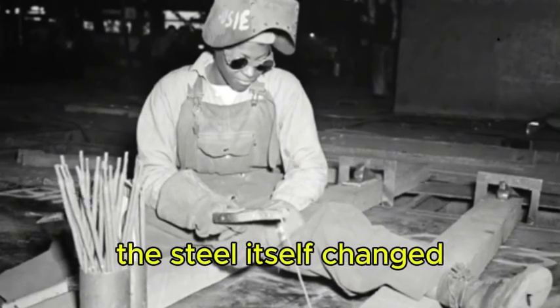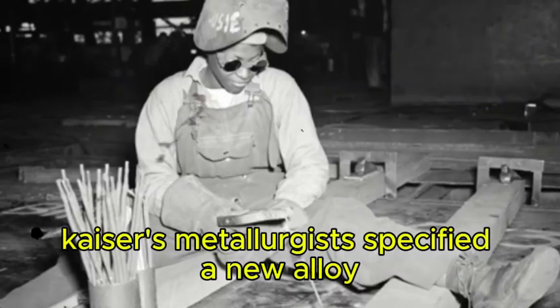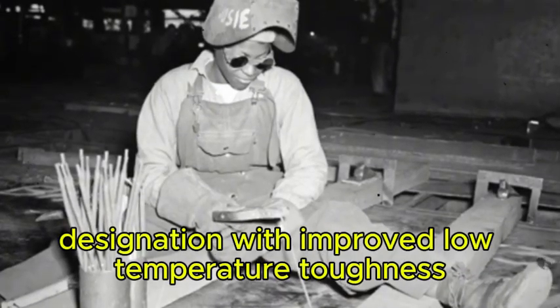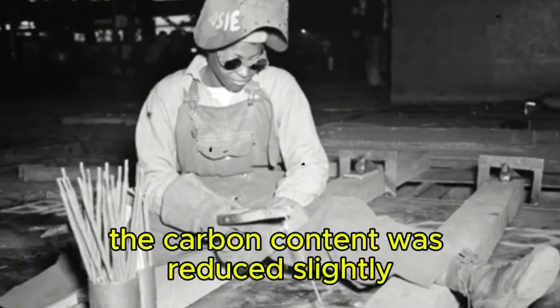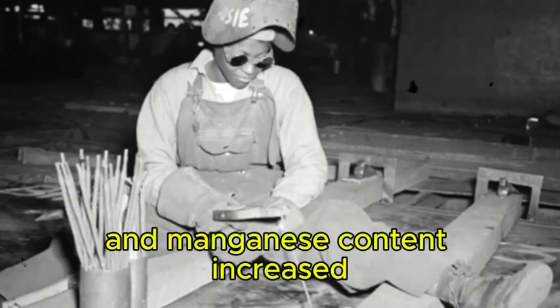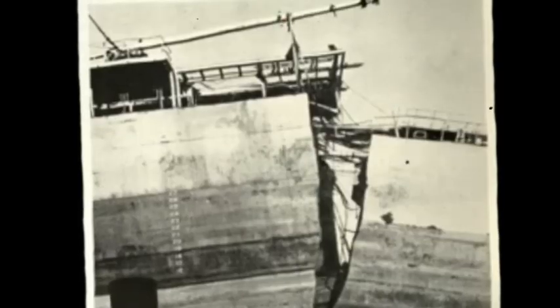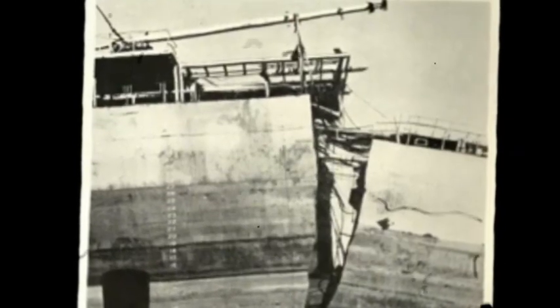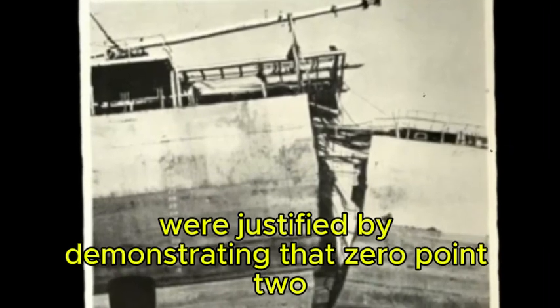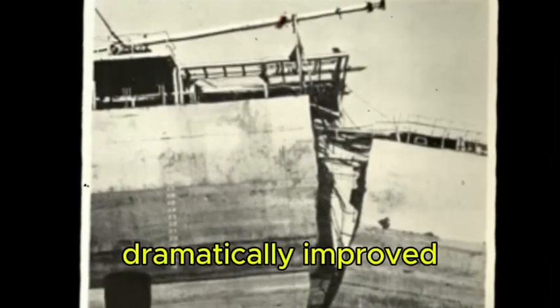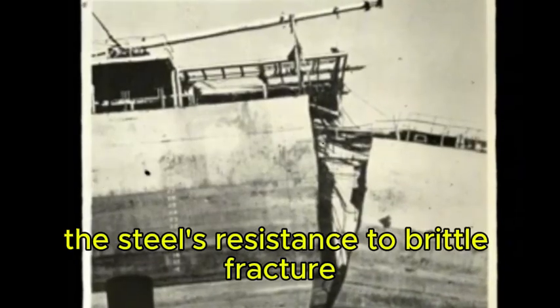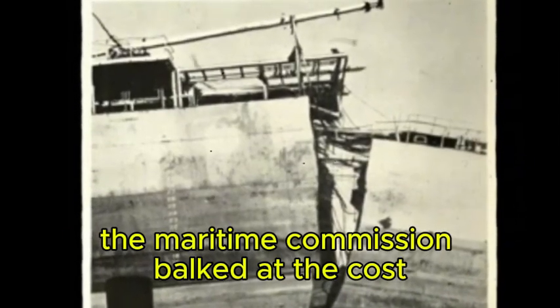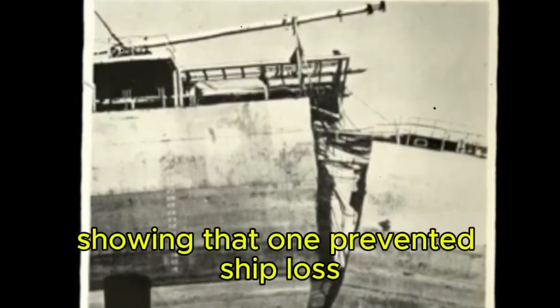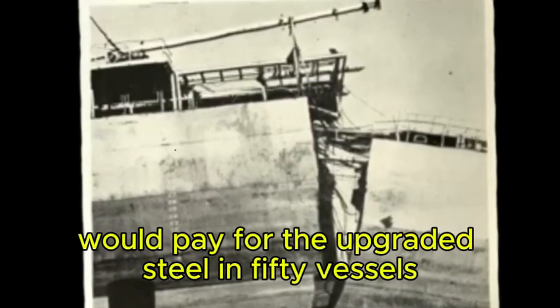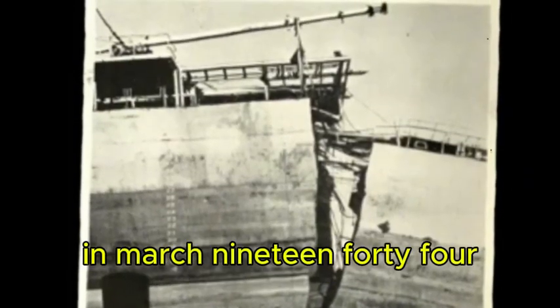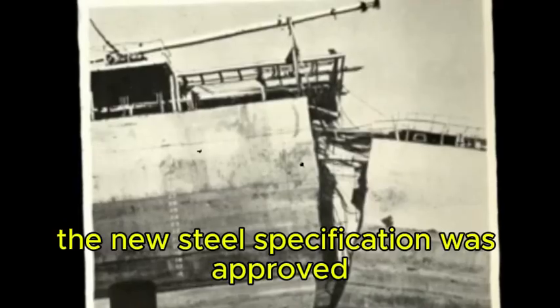The steel itself changed. Kaiser's metallurgists specified a new alloy designation with improved low-temperature toughness. The carbon content was reduced slightly and manganese content increased. Small additions of nickel, expensive and rationed for armor plate, were justified by demonstrating that 0.25% nickel content dramatically improved the steel's resistance to brittle fracture. The Maritime Commission balked at the cost until Kaiser presented calculations showing that one prevented ship loss would pay for the upgraded steel in 50 vessels. In March 1944, the new steel specification was approved.